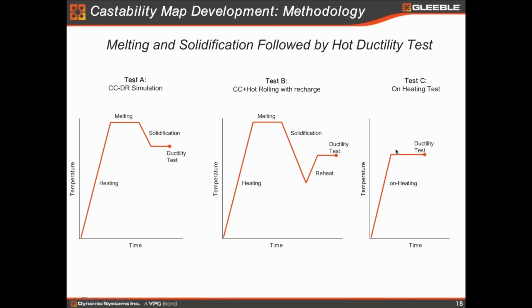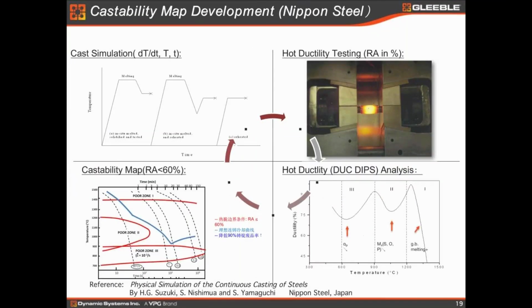And by this design, you can know how bad this casting ductility is. We all know the material ductility will become very bad when it's heated. And actually, the fact is the higher the peak temperature, the worse the ductility is. So melting, of course, is the worst. That is why the melting is so important. So by doing all this kind of testing, you will generate what we call the hot ductility curve, like this.